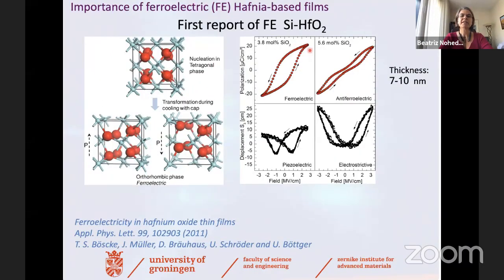Indeed, when one looks carefully at these films, you can see very nice ferroelectric polarization switching loops. And these are films of thicknesses between 7 and 10 nanometers. And this ferroelectricity depends very much on many different things. For example, on doping. Pure hafnia doesn't show ferroelectricity. You have to dope it a little bit with silicon, and many other dopants also work. If you dope it too much, you destroy the ferroelectricity.